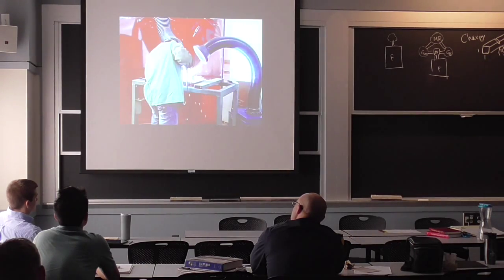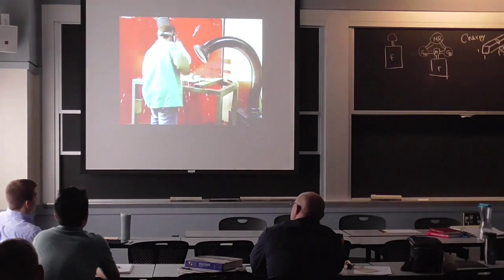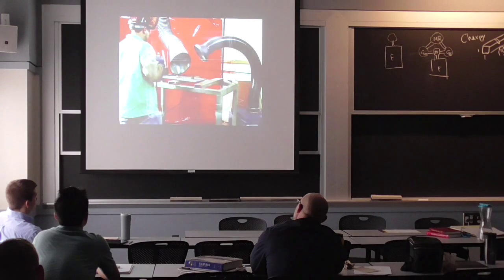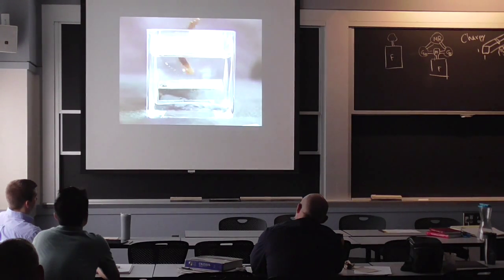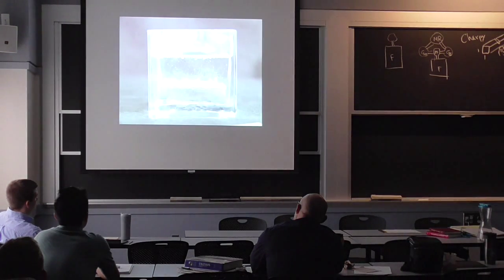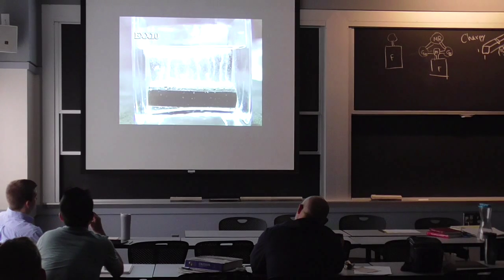Bead-on plate welds are being deposited using the shielded metal arc welding, or stick welding process. Immediately after completion, the welds are placed into mineral oil, so the diffusion of hydrogen from the completed welds can be seen. The first sample was welded with a cellulosic-coated high hydrogen electrode and placed into room temperature mineral oil. A large number of hydrogen bubbles can be seen slowly diffusing from the weld.